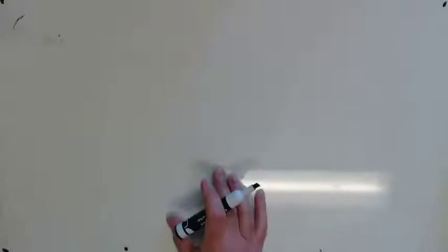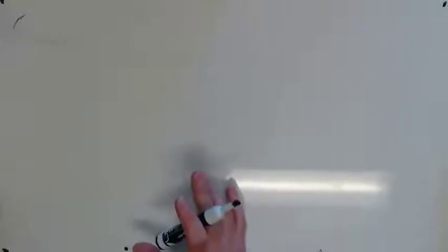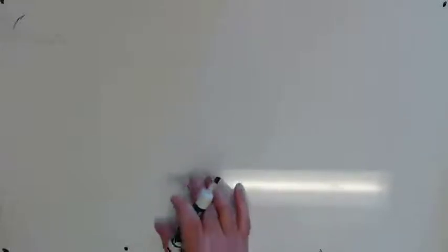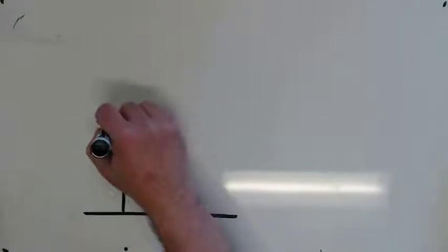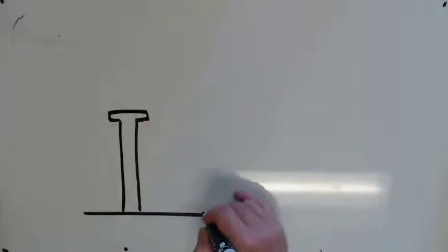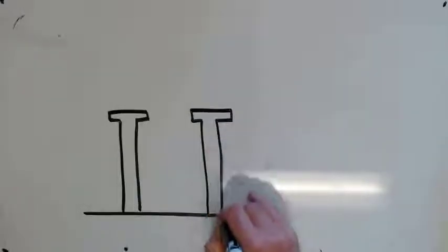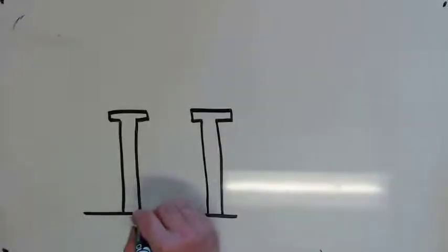Field inspection. At the start of every shift. If you're stud welding. At the start of every shift. You have to test the first two stud welds you make. And how you do that is. You get the machine set up the way you want it. You make your two welds. You visually examine them for 360 degree flash all the way around them.